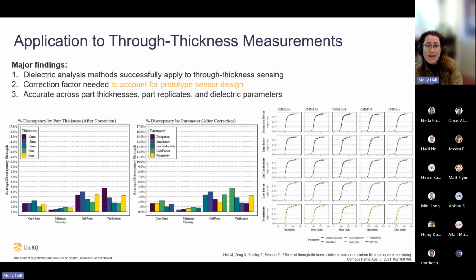I will note that this sensor, because it's a prototype, we did need to add a correction factor, which accounts for the sensor design, temperature compensation, and thickness. But once we applied that, we had very good correlation with all of our properties, all of them being within 5% of what we predicted from our simulation, which is quite close. And yeah, worked out quite well also for both the cure point and the graphical methods as well.